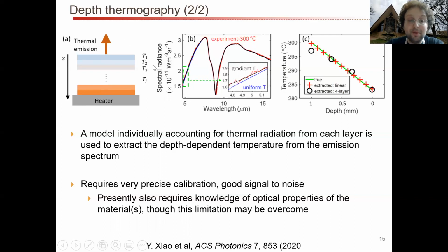And so if we build a model to account for that, Yuja built a very serious model based on fluctuation-dissipation physics, and a thin film, kind of a transfer matrix calculation to essentially figure out how much light is really emerging from each one of these layers and finally emerging and being detected. And we're able to fit this curve. Actually, I'm sorry, this is not a fit. This is just a calculation that accurately describes the experiment. And in this case, this match is really, really perfect.